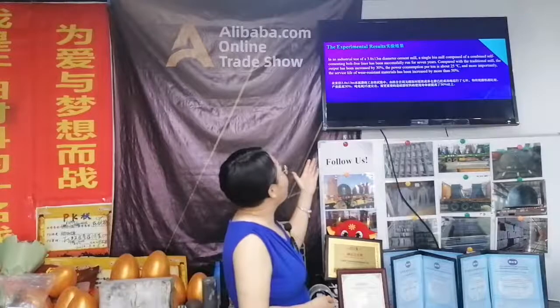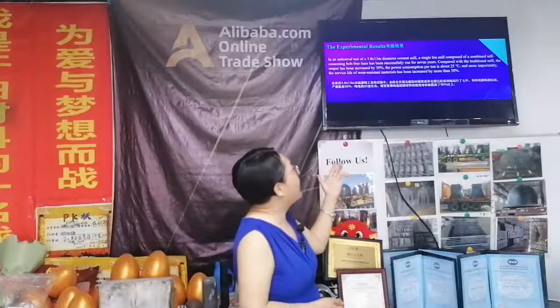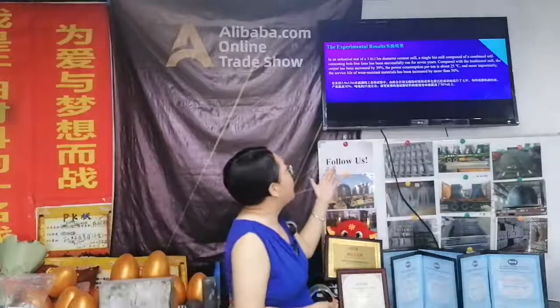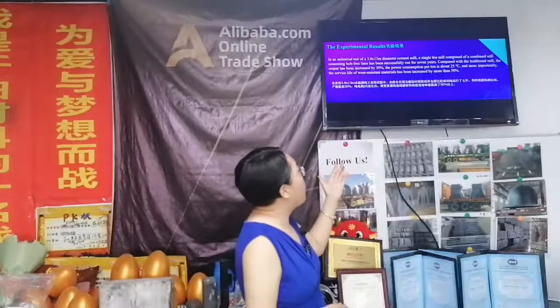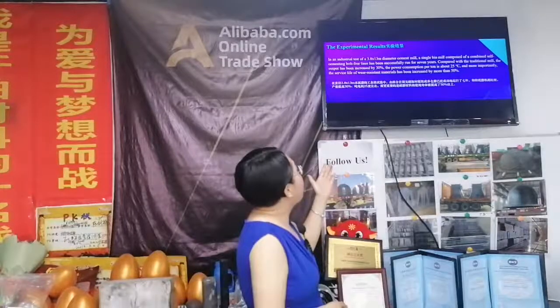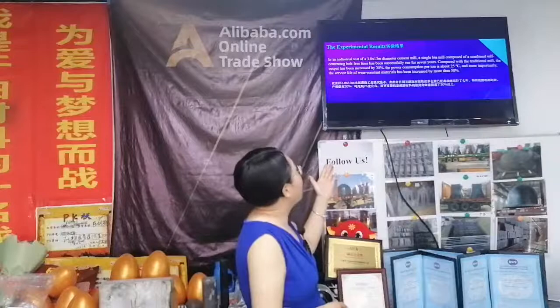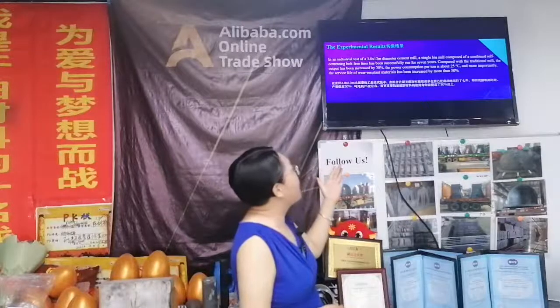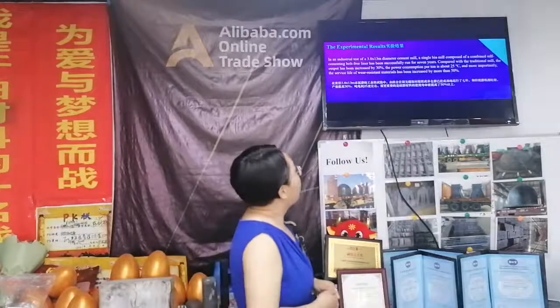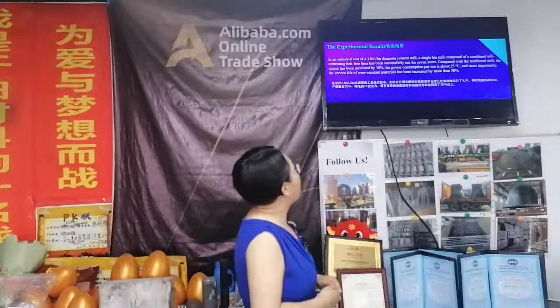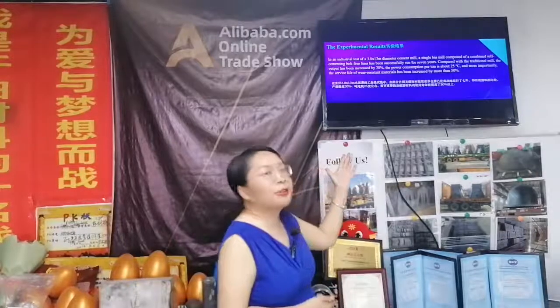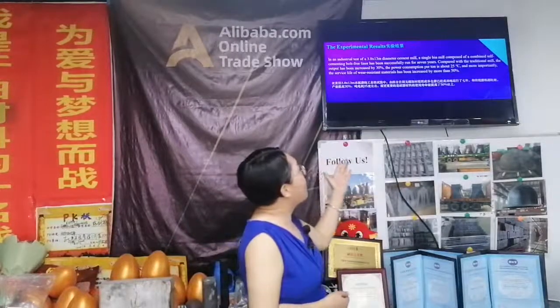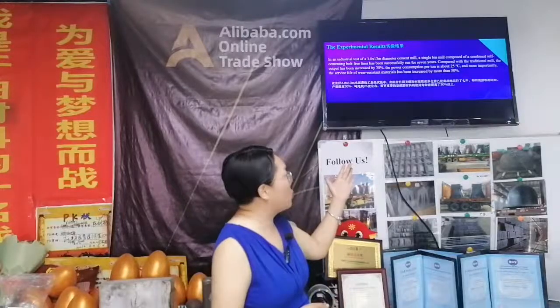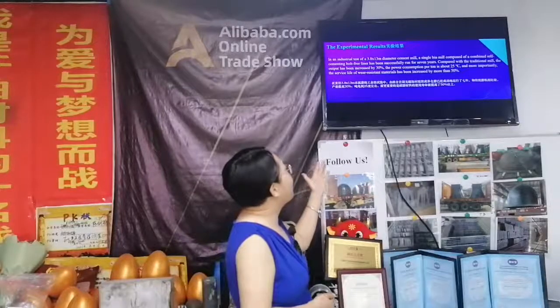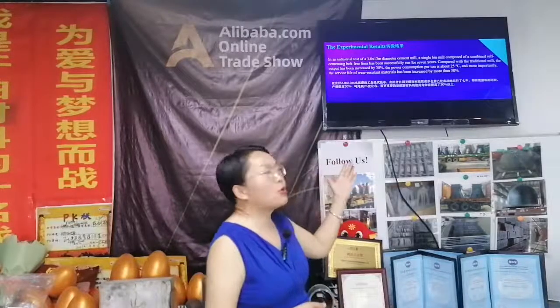In our industrial test of 1.3 meters and 13 meters long cement mill, a single beam mill composed of a combined self-cementing bolt-free liner has been successfully run for 7 years. Compared with the traditional mill, the output has been increased by 30%. The power consumption per ton is about 25 kWh, and more importantly, the service life of wear-resistant materials has been increased by more than 50%.